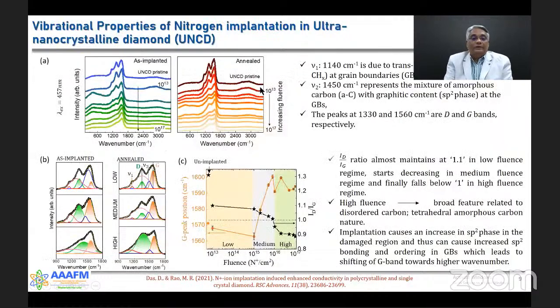Yeah. So the vibrational properties of nitrogen implanted ultra nanocrystalline diamond, the summary of this slide is that the implantation causes an increase in sp2 content especially in the damaged regions, and it causes an increase in sp2 bonding and ordering in grain boundaries, which leads to a shift in the G peak position.